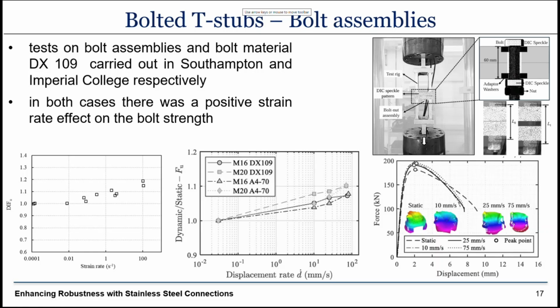Having seen that the bolts govern failure, the bolt behavior at high strain rates is important, and we also had to look into it. So both Imperial College and Southampton, with whom we closely collaborated, did independent tests. At Imperial College, they looked more into the bolt material behavior, so they machined down bolts to extract coupons, and the dynamic increase factor at ultimate stress with increasing strain rate is positive in this case. So with increasing strain rate, we get an increase in the ultimate stress of the bolts.